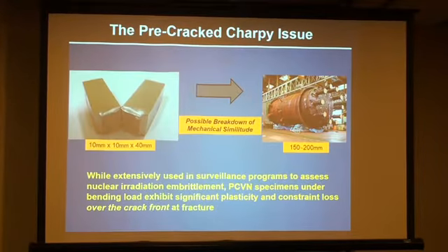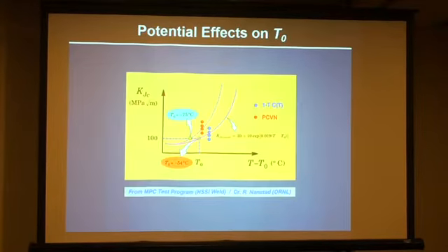However, there is a potentially serious issue here because of the breakdown in the mechanical similitude between a small specimen and a nuclear reactor pressure vessel. And this is because of the strong loss of constraint and strong development of plasticity.